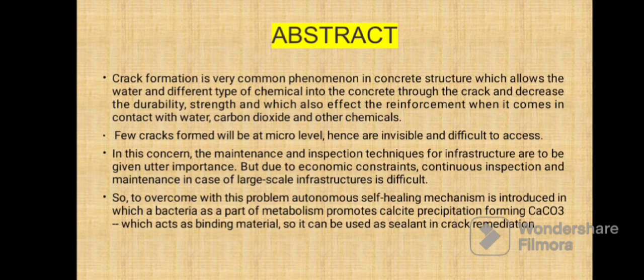Crack formation is a very common phenomenon in concrete structures, which allows water and different types of chemicals into the concrete through the cracks and decreases its durability and strength. It also affects the reinforcement when it comes in contact with water, carbon dioxide and other chemicals. Sometimes the cracks are at a very micro level, hence they are invisible and difficult to access. To overcome this problem, an autonomous self-healing mechanism is introduced in which bacteria, as a part of metabolism, promote calcite precipitation forming CaCO3, which acts as binding material so it can be used as a sealant in crack remedies.